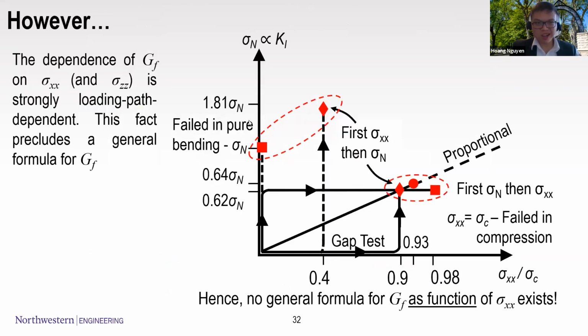So it's good, right? Not quite, because such a relation I mentioned is loading path dependent. It is path dependent in the way that when you apply the crack-parallel stress field first, as in the case of the gap test, and then you apply the force or the bending moment to create fracture, it will result in a different GF from the case when you apply the moment first and then apply the compressive crack-parallel stress. So it negates the purpose of GF as a function of sigma xx, and it calls for using the correct model whenever you have to deal with similar scenarios.